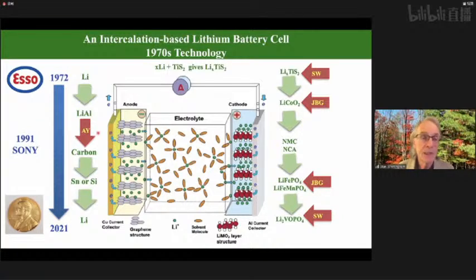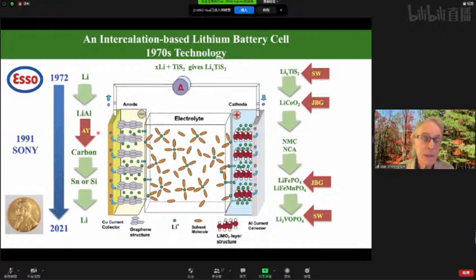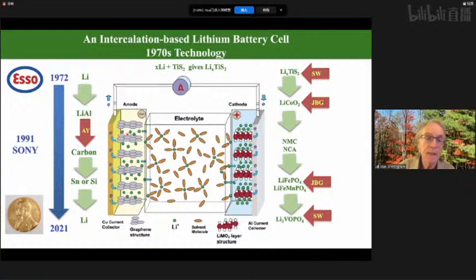Akira Yoshino was interested in polyacetylene as an electrode, and then discovered that graphitic carbons were very good hosts. And that's what I show you right here. This is essentially graphite with lithium between the layers. The challenge with the carbon is you need 72 grams of carbon to store 7 grams of lithium. So not very effective on the weight basis, and the anode also takes up half the volume. So a lot of work now trying to switch to tin or silicon, which react with more than 4 lithium ions, but many challenges there because it expands by more than 300%. So the holy grail is still to go back to lithium, and I'll show you some data on lithium in a moment.